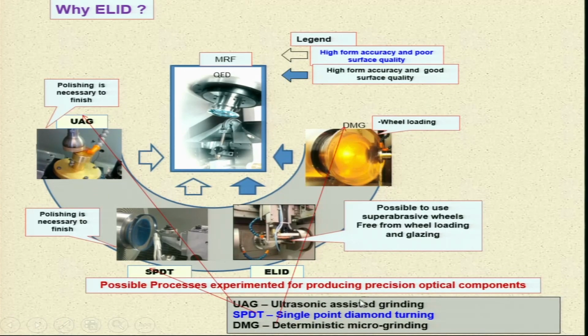Then you have deterministic micro grinding. Your wheel loading is overcome by removing the layers, that is the oxidized layers. So, high form accuracy and poor surface quality, or high form accuracy and good surface quality. After ELID you get a certain surface quality. So, with the help of MRF you can get high form accuracy and good surface quality. So, that is the advantage of combining the ELID and MRF processes. This is the common advantage of any hybrid process, because in a hybrid process you take the advantage of both two or more than two constituent processes.